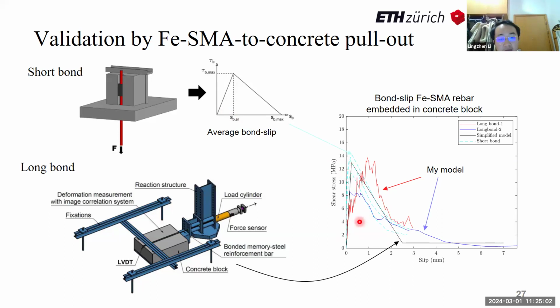My colleague Bernhard Schranz measured 3 local average bond slip behaviors, shown as the dashed blue curves. Then he measured the force-displacement behavior of two joints with longer bond length, 800 millimeters long. Then how do we infer the bond slip behavior for the long bond cases?